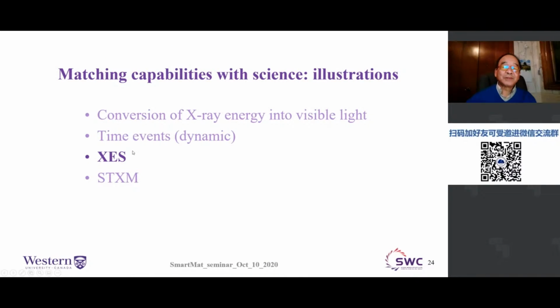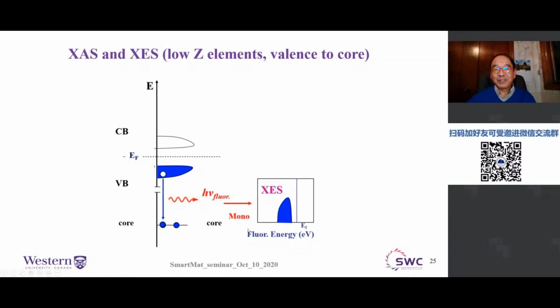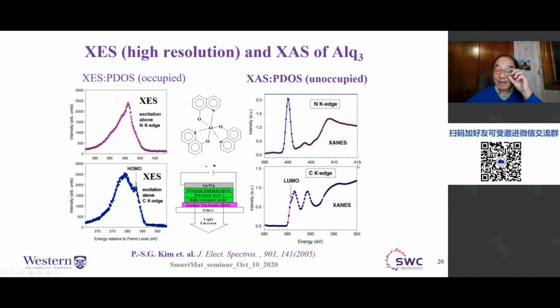So the next experiment is what is known as X-ray emission, which is a fancy word for X-ray fluorescence, right? As I mentioned earlier, this is how you get X-ray emission. I just want to give you an example of a very popular compound, Alq3, for OLED, right? On the right-hand side, we're doing the absorption spectrum, so we're getting the LUMO path and so on, right? And then the XES gives us the occupied density of states. But it's different from the occupied density of states from XPS because this is the nitrogen component and this is the carbon component. And by looking at this, it's very clear the HOMO has mostly carbon, and very little nitrogen. And then by measuring the separation, we can get the LUMO-HOMO gap. So it's a very powerful tool when you combine both of them.